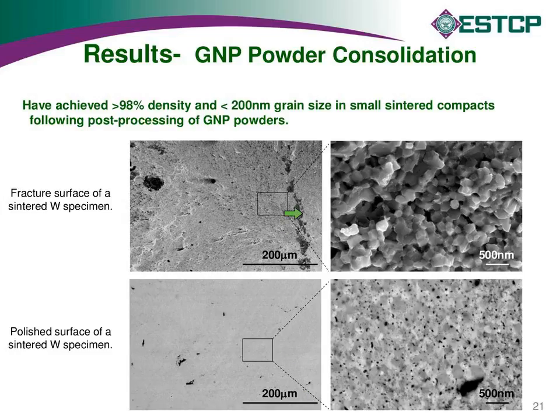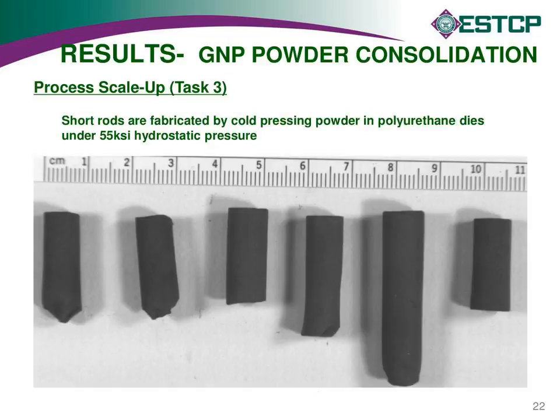Again, this is examples with the 0.5% nickel. Okay, this is basically one of the best microstructures we got. These were only in very small compacts, but we did get on the order of a 200 nanometer grain size in this case, but only in a small sample. So again, the trick is how do we make a bigger sample? Let's go to the next slide.